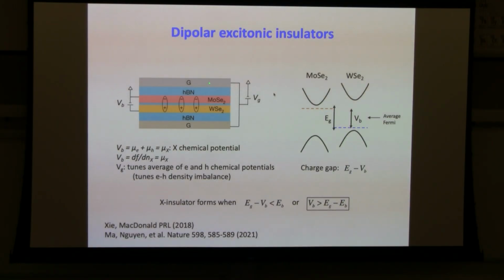And furthermore, we can actually add top-bottom gates to this system here. And that actually allows us to add extra electrons or extra holes into the system, and that would tune the electron-hole density imbalance. And you can think of it that it just tunes the position of this average Fermi level between the orange dash line and the blue dash line. Okay. So there are multiple tunabilities in the system, but the two parameters I will focus on are this VB, which tunes the exciton chemical potential, and the VG here, which would tune the electron-hole imbalance.